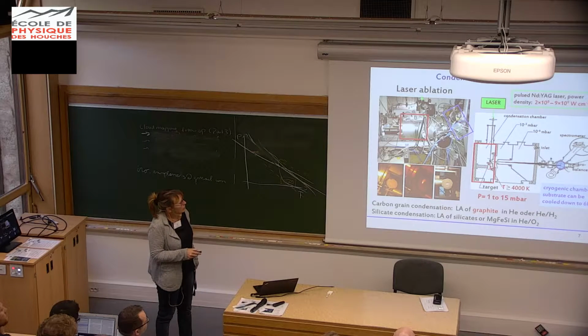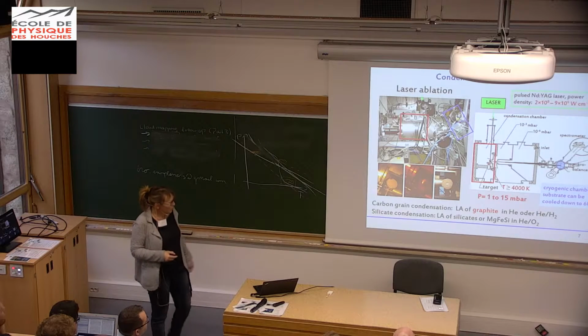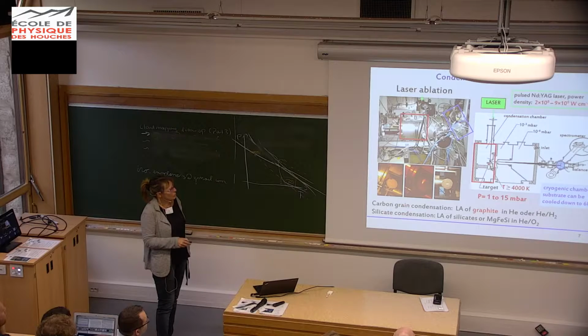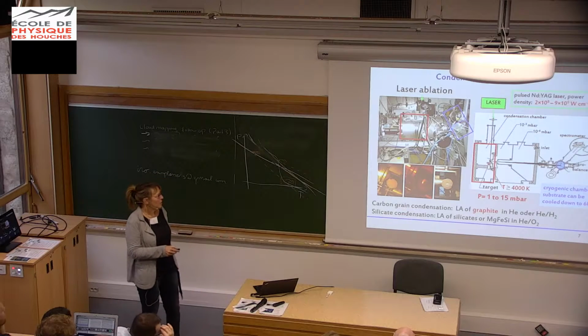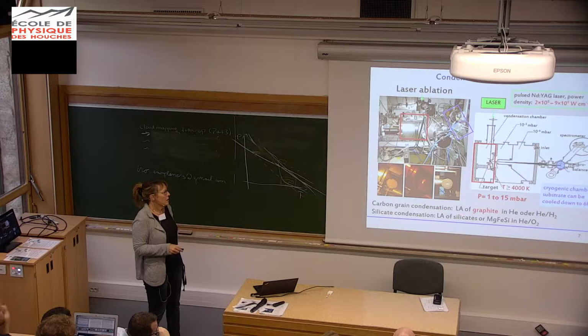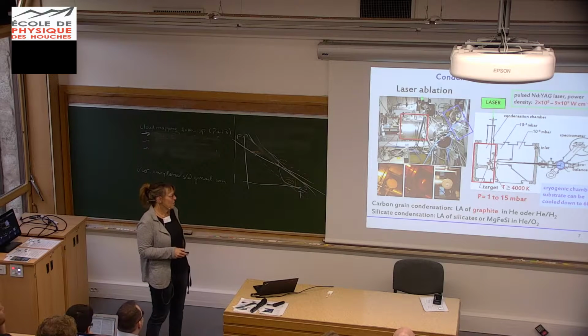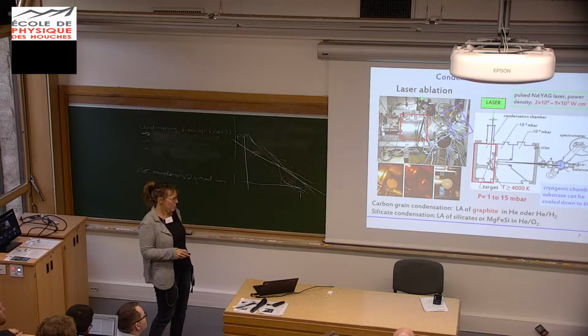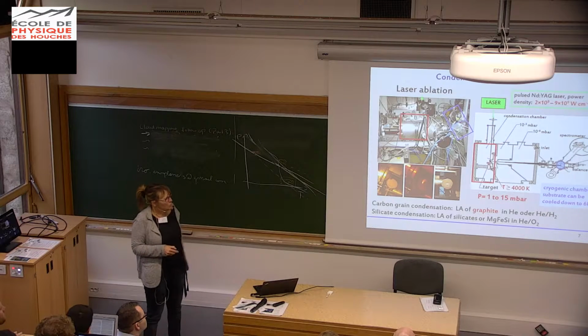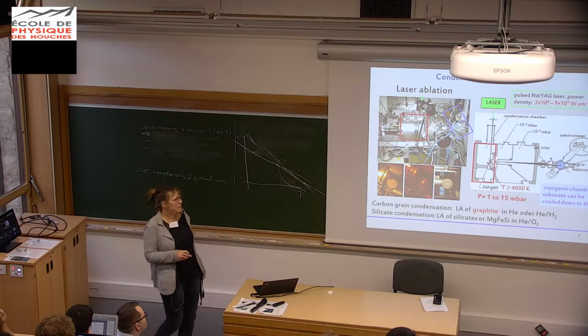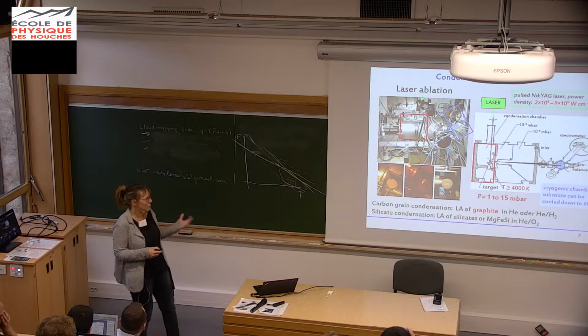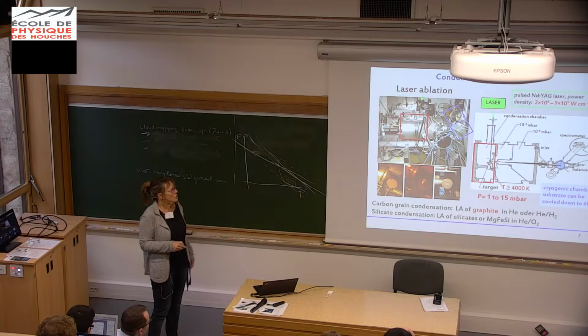In this laser ablation, we can really achieve homogeneous nucleation of silicates or carbonaceous materials, depending on what kind of target we use for the condensation. For carbon, we use graphite, and then we condense in a helium or helium-hydrogen atmosphere. Hydrogen is a reactive gas here and introduces hydrogen into the carbon structure.